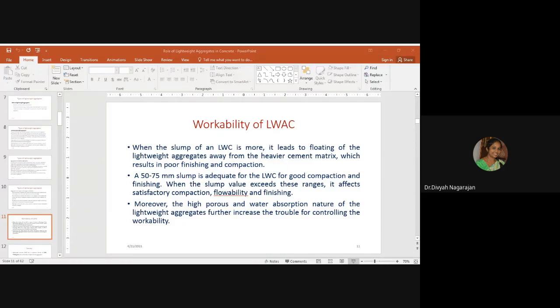High slump is not required for better finishing and compaction of lightweight concrete, as in the case of normal weight concrete, since the work done by the lightweight concrete by its gravity is much lower than that of the normal weight concrete. This reason encouraged the ACI code to limit the slump of the lightweight concrete to 100 mm only for better finishing and compaction.